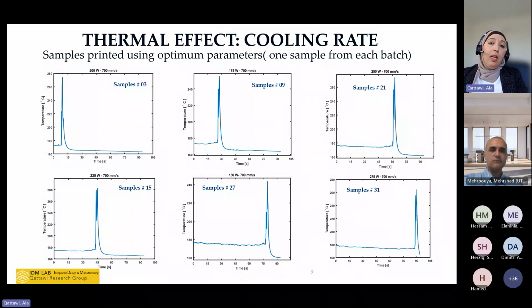In other words, the material, because of the thermal energy that we disperse, can have a different time to cool or go to the temperature of the building plate. And over aggregation of time and over aggregated layers, this makes a huge difference at the end, because eventually we can spot where the thermal cooling rate was irregular. And that will give us exactly where the defect happened, in which layer, at what time, and in what place in the sample.